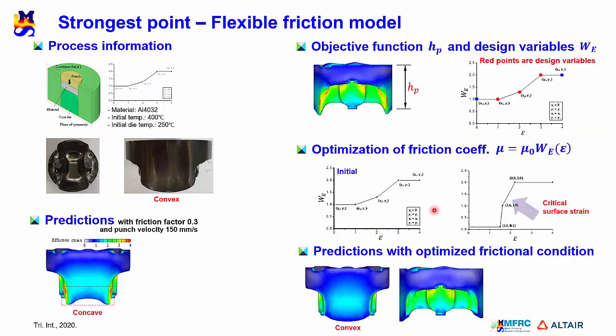For the last strong point of AFDEX, I prepared a tribological example. This is an example distinctly showing the convex shape at the bottom. However, when a constant friction condition was applied, a concave bottom part was predicted. A Korean research institute had tried to predict the concave bottom using various metal-forming simulators under the same conditions for 2 years, only to fail.